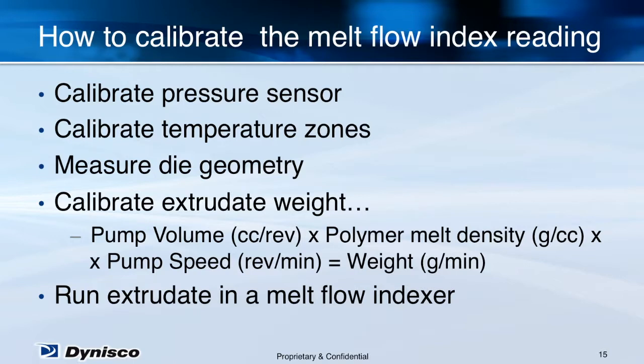To the extent that the weight is not right, either the pump volume or the polymer density parameters usually need to be adjusted because it is unlikely that the RPM measurement on the machine is off. Typically, it's usually the density that should be changed, but the pump is made from steel, so it is a wear item in abrasive or corrosive applications.